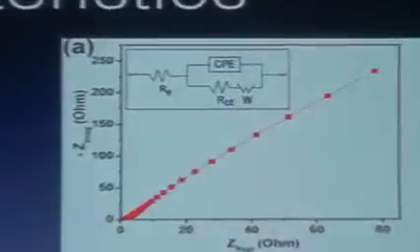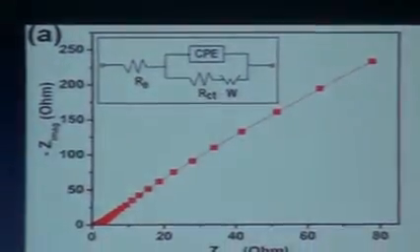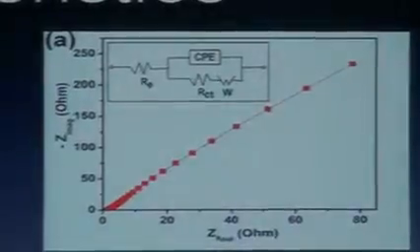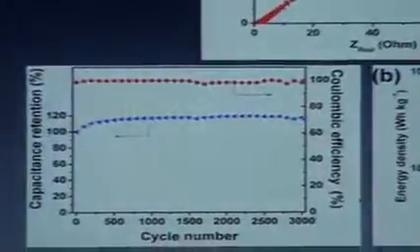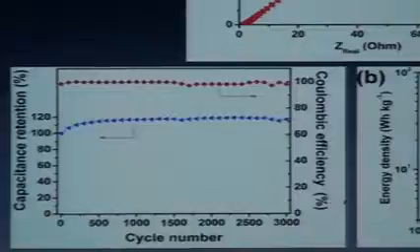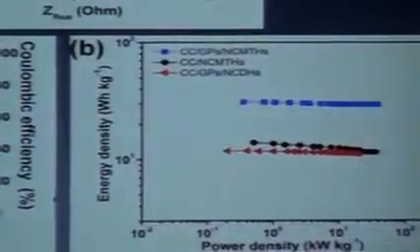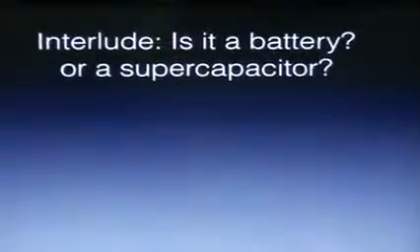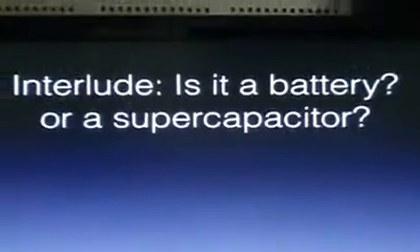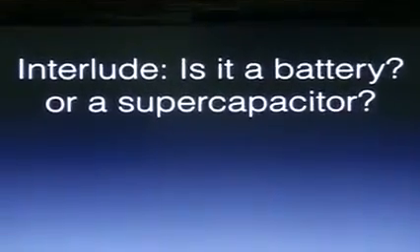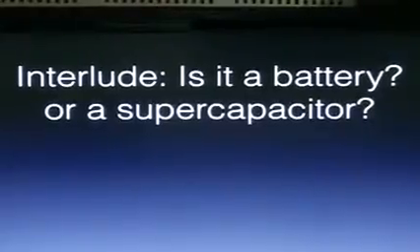And we also had our EIS, right? And so we had this Warburg analysis that we could do. The Warburg Effect is one that has to do with the diffusion of mass, the mass transfer effects, diffusion, and to some extent reaction kinetics in your Faradaic material, your pseudocapacitive material. So one thing that you might ask, especially looking at that CV curve, is: is it a battery or a supercapacitor, right?